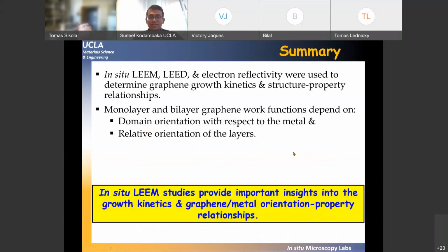So that's the graphene layer growth, and hopefully I gave you some idea of what one can do, which you probably already know if you have been doing LEEM: use electron reflectivity and electron diffraction in combination with the imaging aspects of LEEM. One can get a very good understanding of the orientation, structure, and property relations in two-dimensional layered materials.